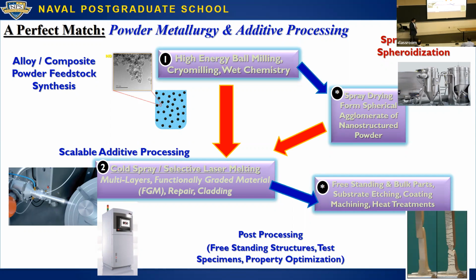Sometimes we may need to have extra steps, for example, with 3D printing. Sometimes you may need to spheroidize a powder. Normally, we try to avoid those extra steps and just go directly from powder synthesis to additive processing. Mostly what I use are cold spray, which is more of a coatings technique, layer by layer, and then selective laser melting, for actually 3D printing pretty complex structures of metals.